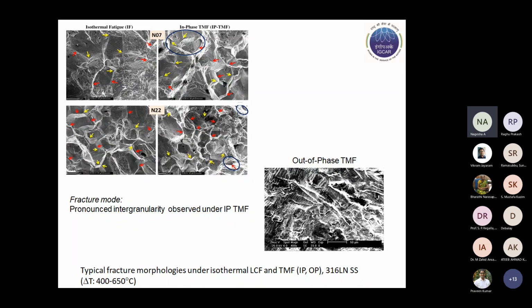We have investigated 316LN with various nitrogen contents also, in order to establish the optimal nitrogen content for the best performance under TMF and creep fatigue interaction. So similar is the situation across all the nitrogen contents. Here one can see the extensive grain boundary damage in the case of IP cycling, compared to a mixed mode dominated by transgranular cracking in the case of isothermal and also in the case of out of phase TMF.